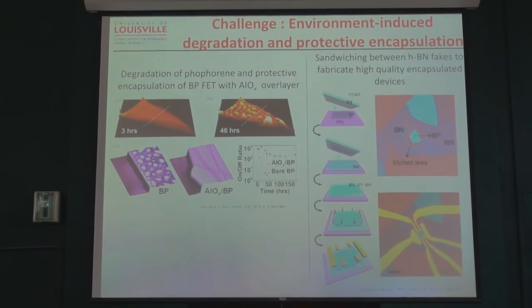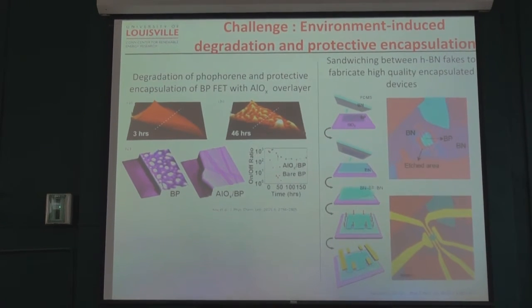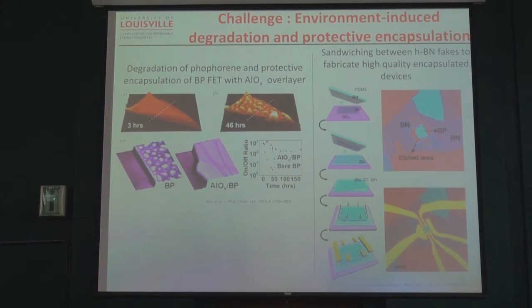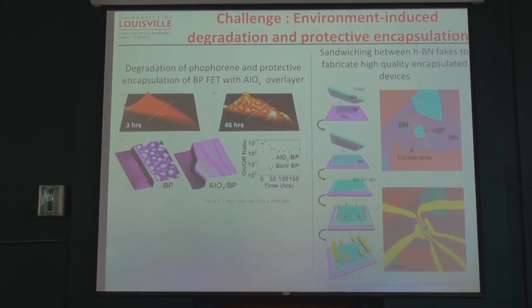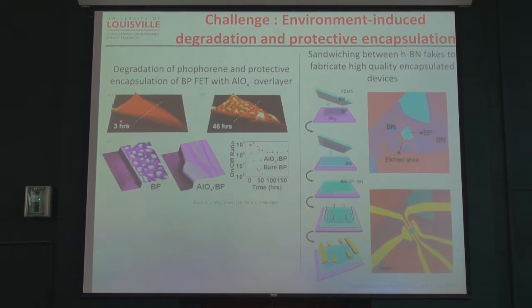But the biggest problem for phosphorene is that it is very unstable in air. If you expose it to air, it degrades. So that's the biggest problem for phosphorene. You can see how the AFM picture looks after 3 hours. In 46 hours, you can see how the surface becomes pretty bad, the oxidation. Looks like a pizza. Yeah, exactly. Here you can see it's pretty nice. So that's why once you make phosphorene, you have to cover it with some capping layer. Here, some people, once they have this, the BP is black phosphorus, then this is hexagonal boron nitride, right? You can cover phosphorene with boron nitride, right?